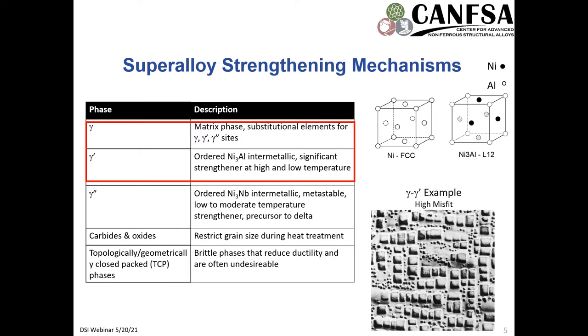Within the gamma, there's predominantly just substitutional strengthening going on. We have various elements such as cobalt and chromium that act as substitutional strengthening elements for this phase. And in the gamma prime, we have here on the right, it's the Ni3Al or the L12 structure. And we have nickel at the face center sites and aluminum at the corner sites. There are various elements that can substitute for either the nickel or the aluminum. Oftentimes you may see titanium substituted for the aluminum at those sites.